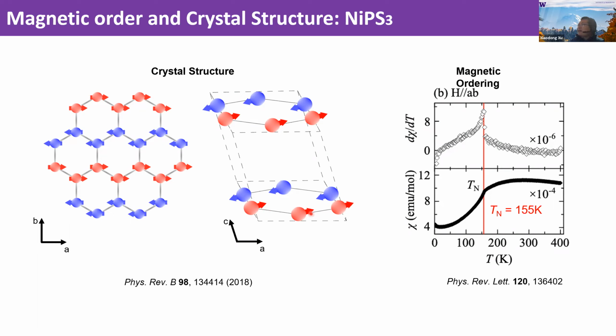Okay. And there is already a lot of work done on bulk crystals of nickel phosphotrisulfide. For example, here this work studied the magnetic susceptibility as a function of temperature, and you can clearly see the magnetic phase transition happen at about 150 kelvins. We'll go back to this particular data a little later.